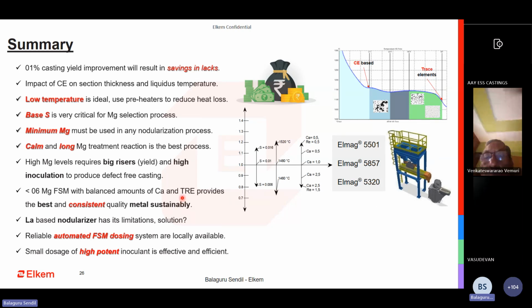And when it comes to inoculant, it is always better to go for smaller additions of high potent rather than large additions of ineffective inoculants. Calcium barium based is quite common, but it has been outdated. So we have cerium based inoculant, we have coated inoculants which are more potent. When you're shifting to that more potent inoculant, you need to add less. You cannot add 0.4, and then it is not a very economical way to do that.